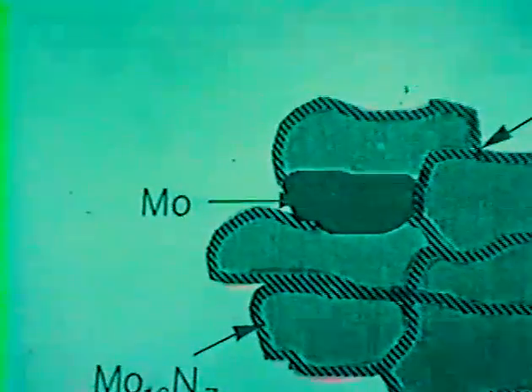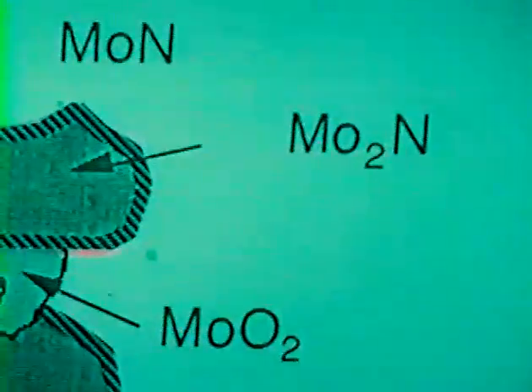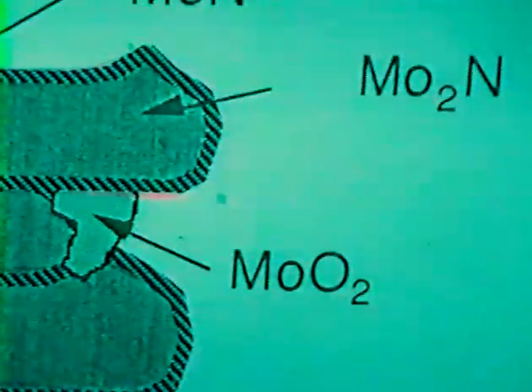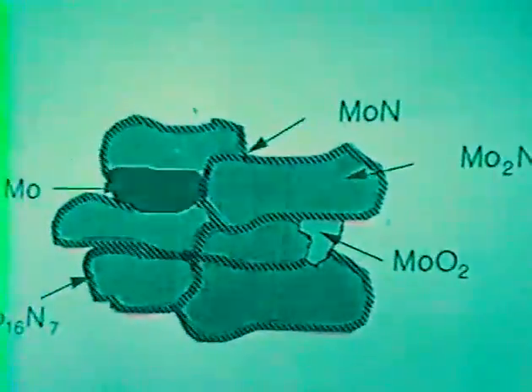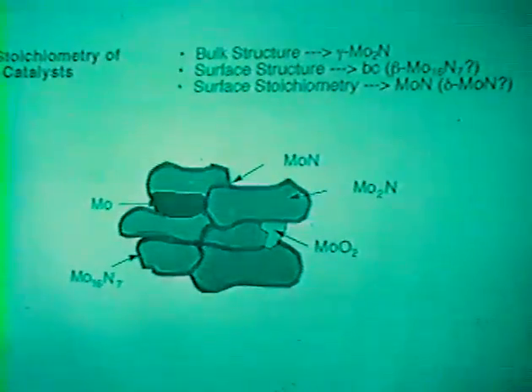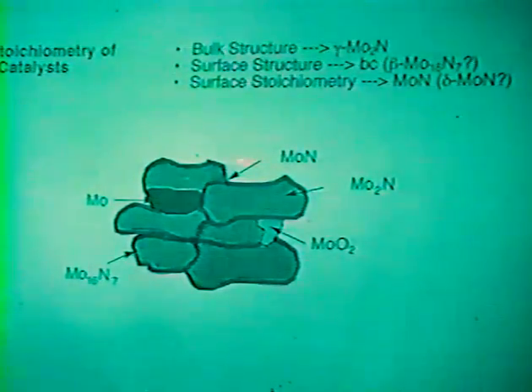To summarize briefly this first part, there is clear evidence that the bulk structure is the FCC molybdenum nitride. The surface structure is body-centered tetragonal. Body-centered. It's possible that it's molybdenum or this beta molybdenum nitride. The surface stoichiometry of the most interesting materials appears to have a nitrogen to moly ratio of about 1, which suggests that perhaps if we were trying to align this with the equilibrium structure, perhaps it's the delta phase. This is a schematic to illustrate that. It also helps us jump into the next part of this talk.